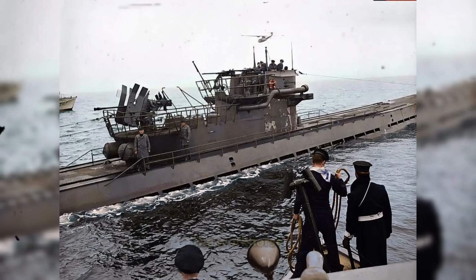The Type 7 was the workhorse of the Kriegsmarine's undersea fleet, sturdy, compact, and lethal. Over 700 units were built between 1936 and 1945. Each was a pressure vessel of welded steel, the central cylinder 21 millimeters thick, designed to endure enormous external forces. The steel, St 52, was rated at 520 megapascals tensile strength, good enough to resist collapse well beyond 250 meters. Engineers built in a safety margin.